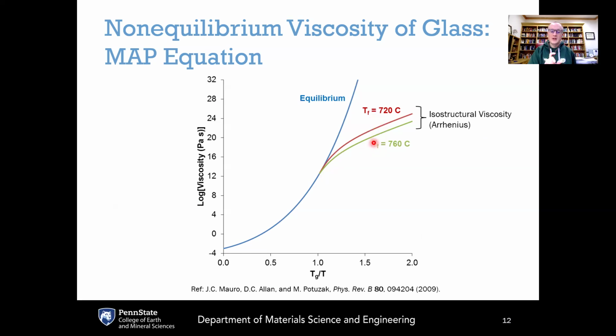Just going between these two different curves here, if you just draw a vertical line through here, this would be comparing the viscosities of the same glass composition, the same temperature, the same chemistry, but just two different cooling paths. And if you have a faster cooling rate with a higher fictive temperature, that viscosity can be one, two, even more than two orders of magnitude lower compared to the viscosity of the slower cooling rate. The other thing you'll note is that the viscosity of the glass here is actually quite a bit lower than the viscosity of the liquid at the same temperature. And so the viscosity of the glass could actually be surprisingly low compared to what you might think intuitively.